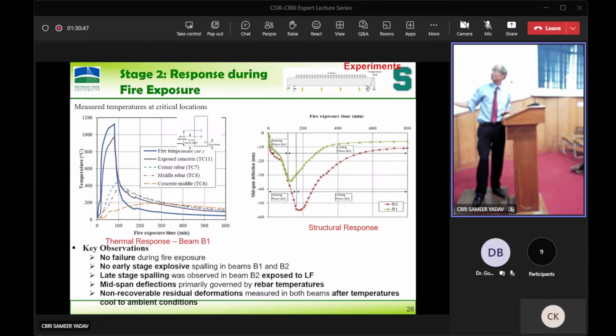Then you carry out the fire resistance test on the beam by subjecting it to fire, right? And we look at this, this is the fire load, just like it was in that room. It depends on the fuel load. You can calculate the fire curve. I'll show you quickly. Then this is the temperatures in the rebar. This is the temperatures in the concrete. At various places you need to measure using thermometer instrumentation. Then this is the deflection. You look at this, this is the one subjected beam. We tested these 2 beams.